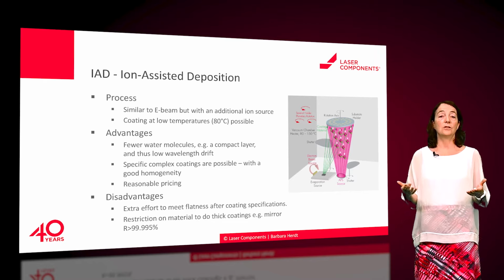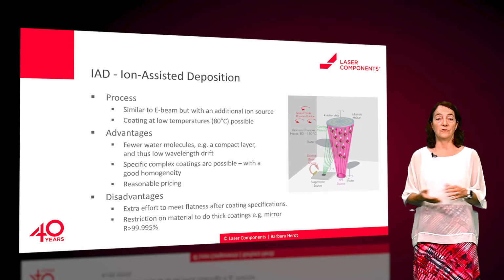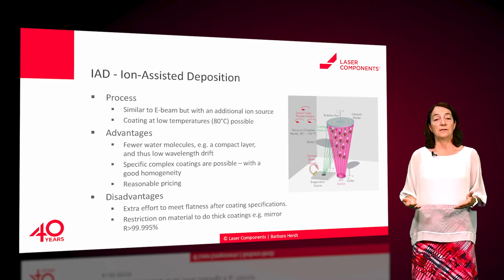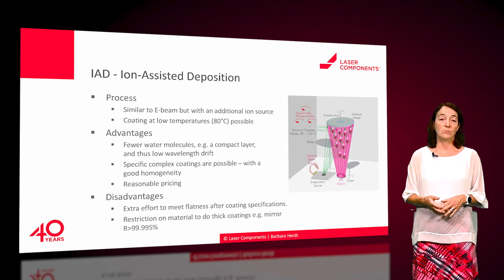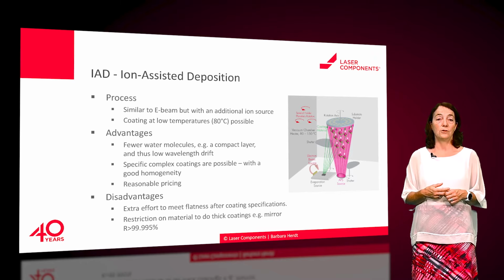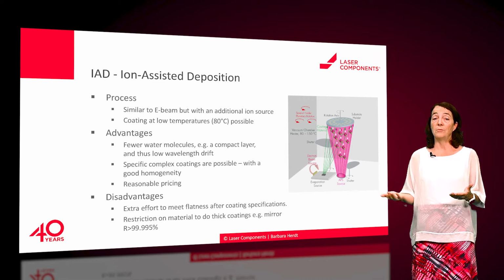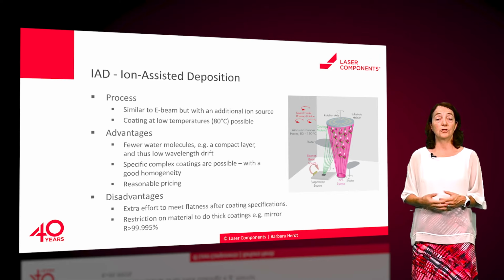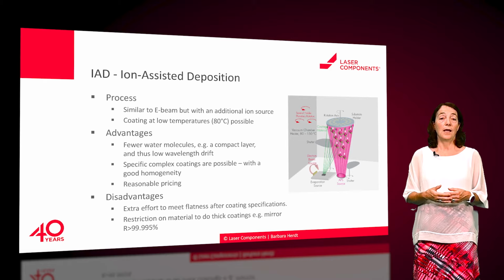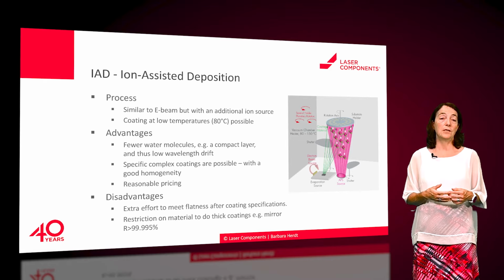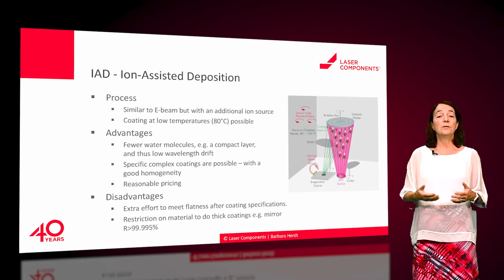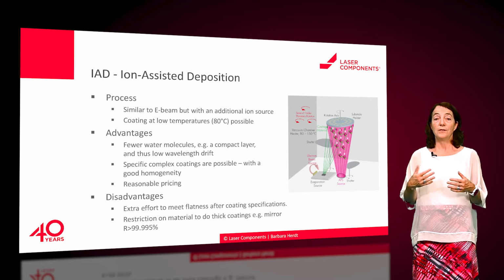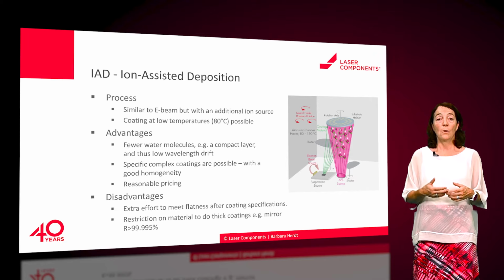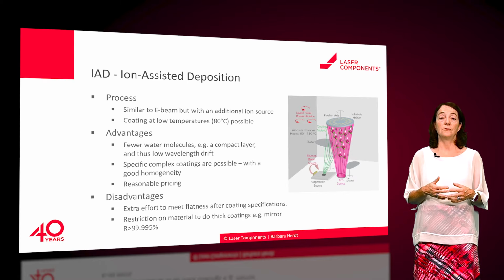However, the high dense coating is paid with higher stress on the substrate. This can be compensated if critical for the application, but on a higher effort, therefore the price will increase. Another disadvantage of this technology, especially if compared to IBS, is that there are some restrictions in total layer thickness, and there is not enough coating material available. This will be improved in beginning of 2023, when we are getting the next generation of IAD chamber.